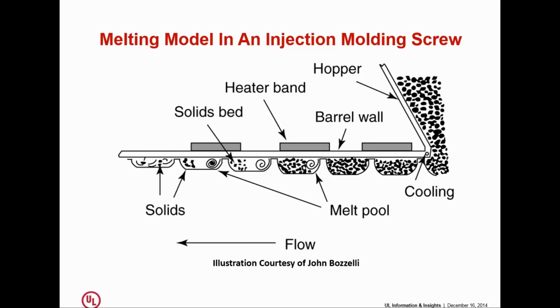The model for this, and the reason we have a problem with this design, is because as we develop the melt pool, and the melt pool and the solid bed are traveling forward, if, and this is usually the case, not if, but when we get to the front, and we don't have all the pellets melted, the solid bed eventually will break up, and it will basically now become like ice cubes in a glass of water.